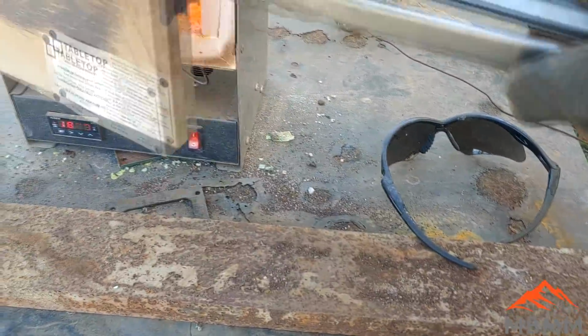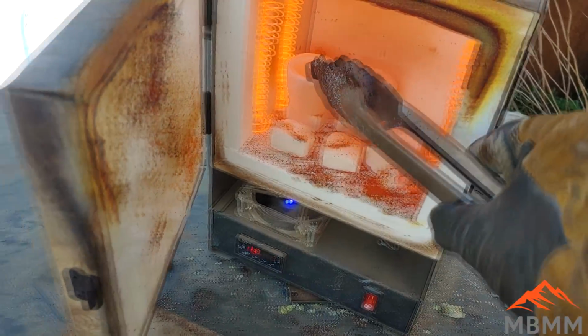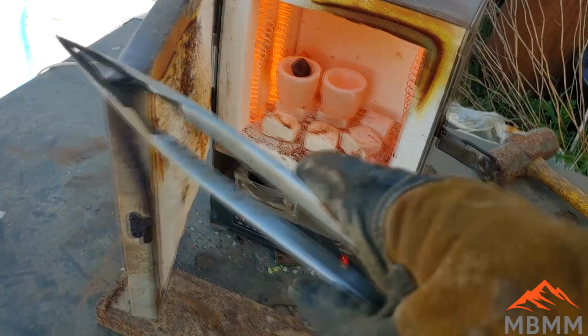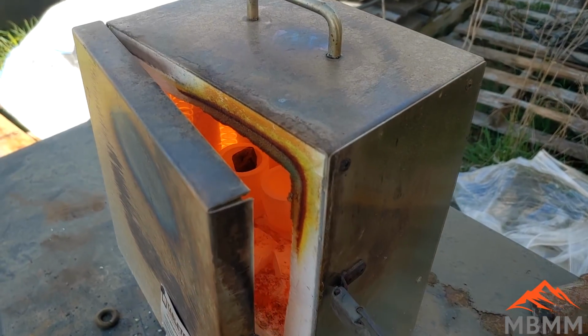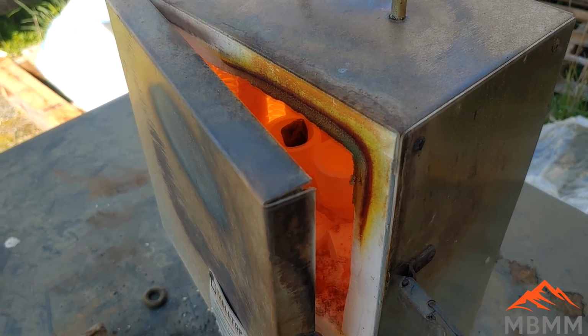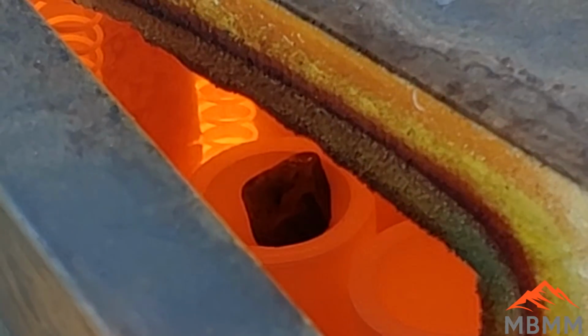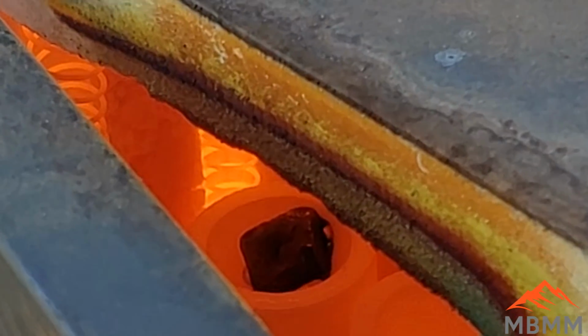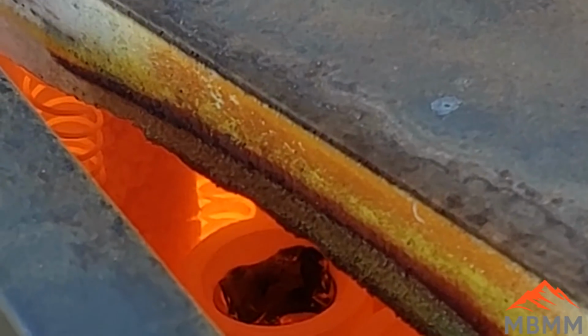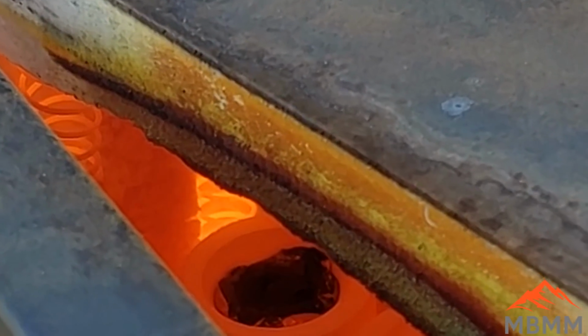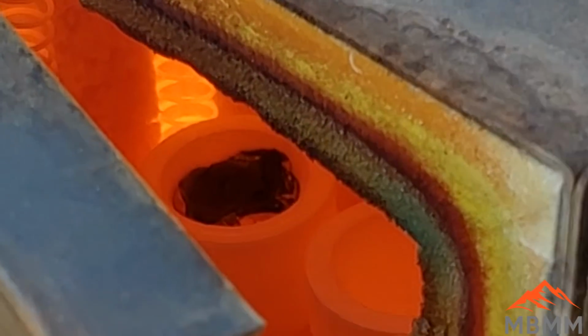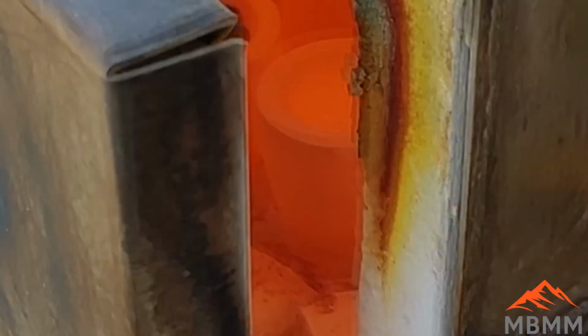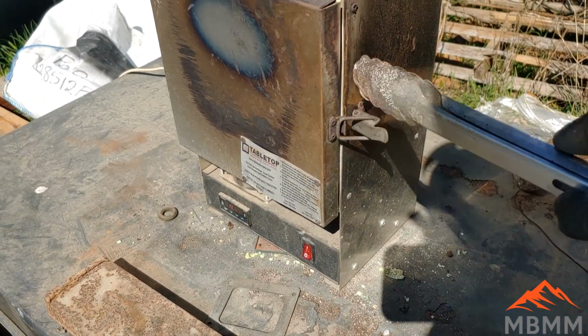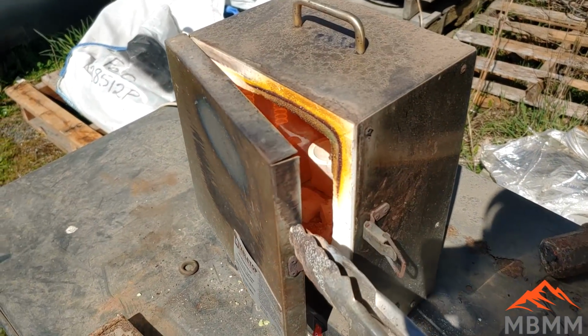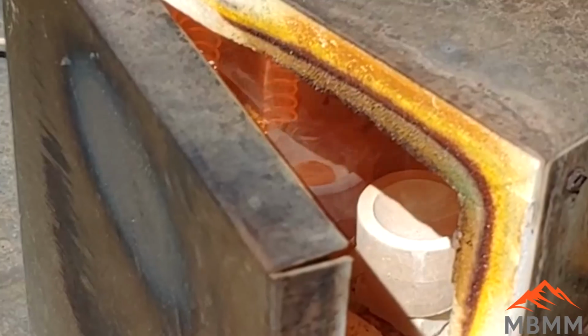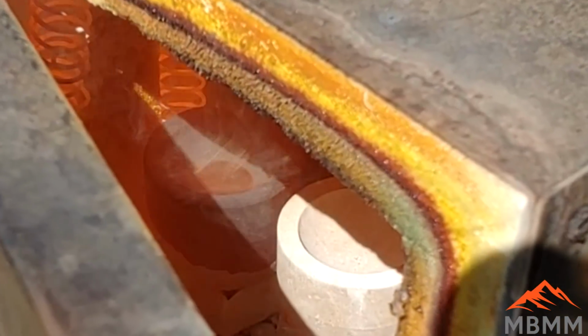I'm going to put this in a cupel, and the lead is going to oxidize at a very high temperature. The furnace is set at about 1850 degrees Fahrenheit. That's going to melt the lead, and the lead is going to oxidize in the oxygen-rich environment in the atmosphere. At 1850 Fahrenheit, that lead oxide is molten, and so it will start to roll off that liquid lead bead in the furnace, and the lead oxide will be absorbed by the cupel.